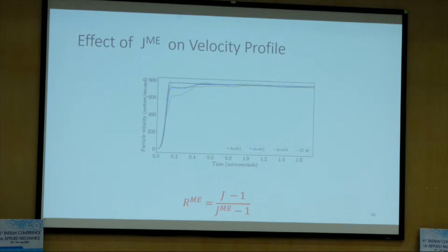Right? Whereas brittle materials under compression expand inside at the crack tip, the flat tip. So that means the bulk modulus is degraded due to tensile crack opening at the tip. That's a mechanism invented or derived and proved by several people. Hori and Nemat-Nasser is one of them.